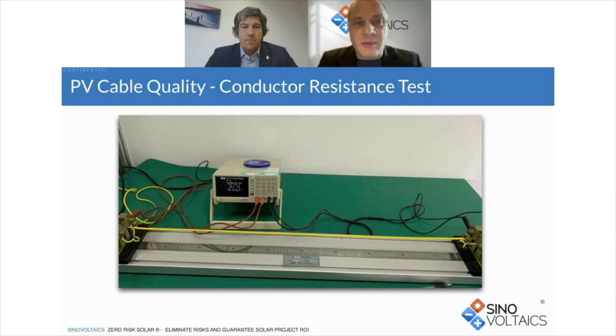One of the common and important tests is the conductor resistance test in line with the applicable cable cross-section. At a given temperature, the resistance of the conductor, which is usually made either of aluminum or tin-coated copper, needs to meet a certain value. If resistance is too high, then simply speaking, and in line with Ohm's law, there is a higher impedance on the current flow, and therefore the cable is less electrically conductive, and there are also transmission losses. So it also means there's more heat. And this is one of the quality issues our team encounters with bad quality workmanship at cable factories.